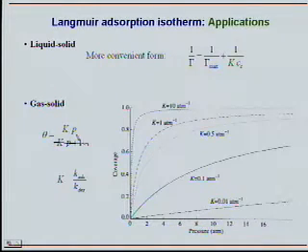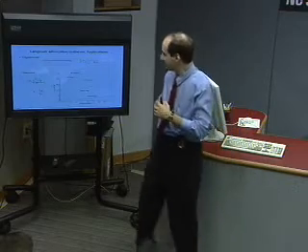The same goes for surfactant. How do you measure surfactant concentration on the surface? This is a non-trivial problem, and there are good methods to do that. Of course, you can use infrared and so on. One other method is to measure the surface potential and relate it to the degree of charging of the surfactant on the surface and then to the surfactant concentration. So there are methods for measuring adsorption, but they are not that good. That's why for surfactant you don't want to measure adsorption. You want to measure interfacial tension and then calculate the adsorption from the Gibbs isotherm, rather than trying to measure directly how much surfactant you have on the surface.